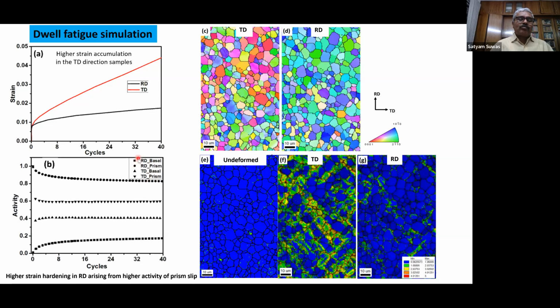So the square and the circular ones are for RD, the top one and the bottom one for RD basal and prismatic slip, while the two types of triangle, inverted and rectangles, indicate TD type of samples. And this was predicted, and the microstructure was generated like this. So we could see here that in the case of the TD sample, there are a lot of situations where heterogeneities have come in the material, right? Compared to the RD type of situation, where a large number of grains do not accumulate strain. So this change in color is a clear indication of the strain accumulation in this case.